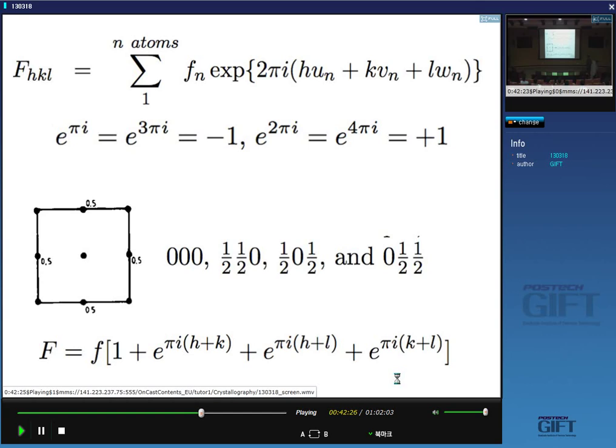And our unit cell has a certain number of atoms, which is N atoms. So if it is a primitive cubic, and the motif is just one atom, then we have just one atom in the cell. If it's cubic F and the motif is just one atom per lattice point, then we have four atoms in the cell, so N would be four. And this is the scattering power of the atom. It's an atomic scattering factor. Okay? So you shine some rays onto that atom and then it scatters them. And what is the ratio of the intensities of the scattered and incident beam? So this is the scattering power of an atom. It will vary depending on the atomic number.